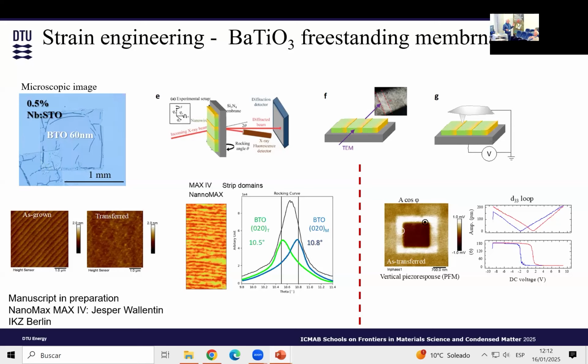And then the first thing that we thought was, okay, maybe we can see a domain structure in the material. So what we did is we took the material in the chamber here, and we heated it up to 200 degrees. Nothing happened. They're all the same. The distances remain the same. Everything is the same. Nothing changed. And then we thought, okay, maybe it's not a domain because you were supposed to see some changes at about 140. So maybe it's not the case.